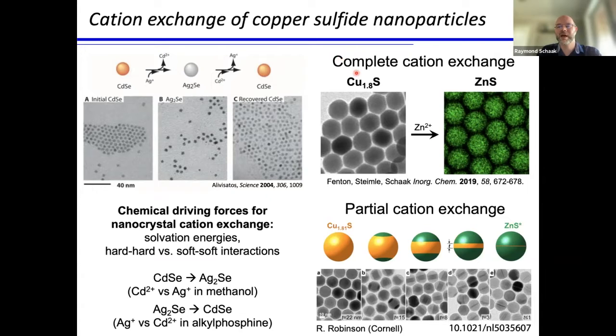These cation exchange reactions can be carried out to completion, which is pretty common, so for example going from copper sulfide to zinc sulfide, but they can also be arrested before going to completion so that partial cation exchange is possible. And this is really powerful work that inspired our group quite a bit, from Richard Robinson's group at Cornell. This is showing copper sulfide spherical particles and doing a partial cation exchange with zinc, where it forms these really neat sandwich type structures that break the symmetry of the sphere.